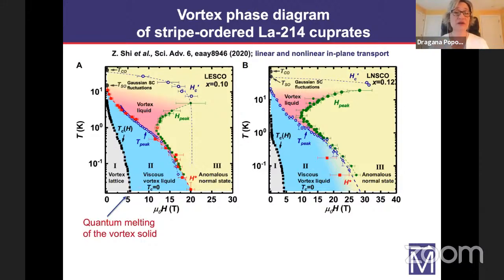The green symbols represent the positions of the peak in the magnetoresistance at different temperatures, and these red symbols represent the boundary between non-ohmic and ohmic regimes. And finally, the blue open diamonds are the positions of the peak in the temperature dependence. So below this peak, we have metallic or superconducting-like behavior, the drop of resistivity with decreasing temperature. And outside of this region, we have insulating-like behavior. So what we see here is that there is a wide range of fields of 15 or 20 Tesla that separates this vortex solid from the high field normal state.